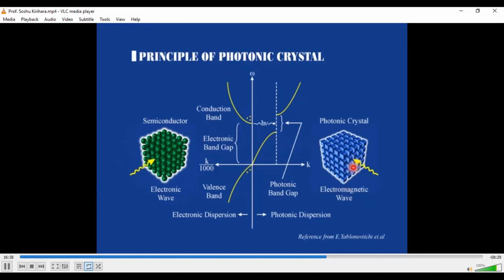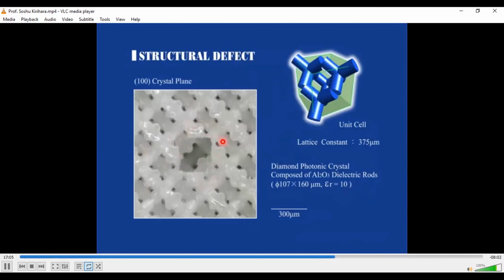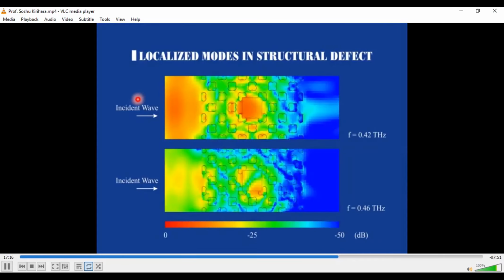This figure shows a point defect introduced in the perfect photonic band gap. Of course, this hole was fabricated by the stereolithographic additive manufacturing process. This figure shows a calculated result. In this case, the incident wave is localized and resonates here, and all around here is a perfect reflection structure, making a standing wave that increases the power and transmits to the opposite side. In this case, a half wavelength is localized here, and in this case, one wavelength is localized in this direction. And this electromagnetic wave only transmits to the opposite side.